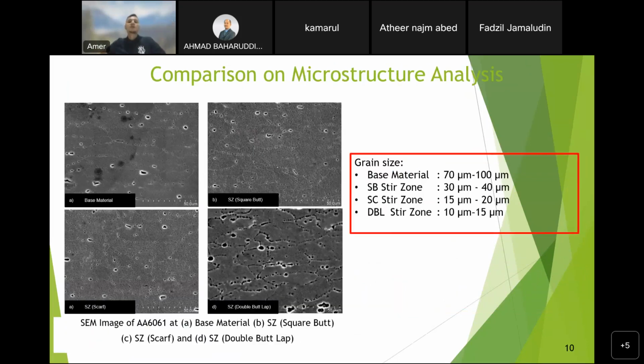Okay, this is the comparison of microstructure analysis. To see the difference in microstructure for each joint, scanning electron microscopy, SEM, will be used. Before it can be seen under the SEM, the sample must first be polished until it reaches a mirror surface finish, and then the etching process is done by dipping the sample into etchant for 15 to 30 seconds.